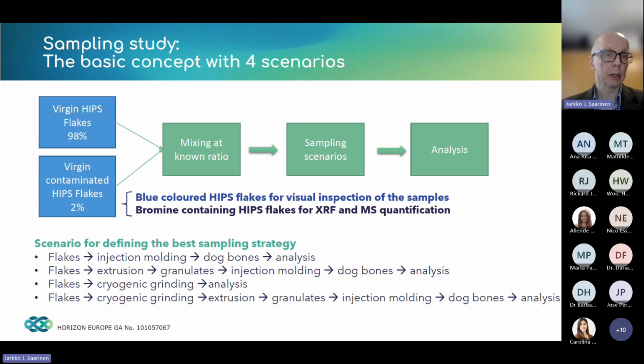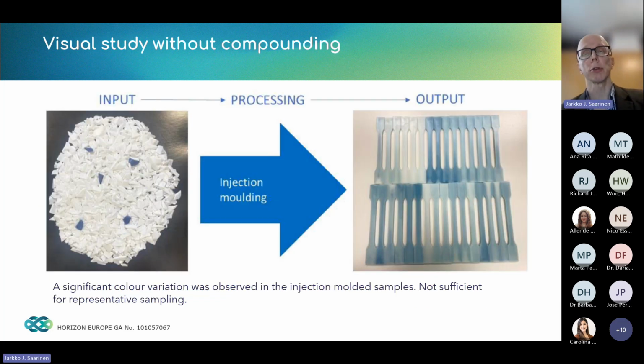So as a starting point, if you just consider a visual study of the first scenario, we have an input material, the white flakes of the high-impact polystyrene, and then we have the colored ones mixed in with a small ratio. We just do the injection molding, and on the right-hand side, you can see the output of this approach. What we see, as one would expect, is that it heavily depends on the odds of having blue-colored flakes in the stream as you are making the dog bones. So we do see a significant variation in the output stream.